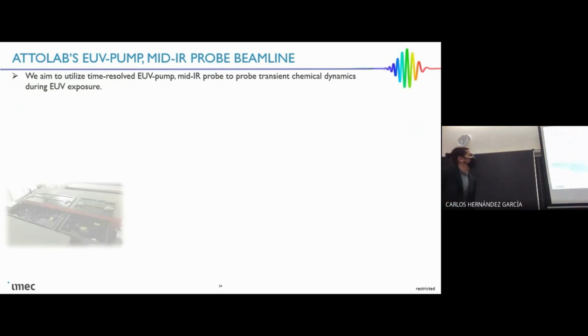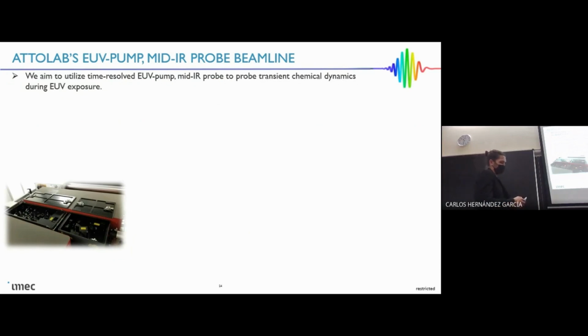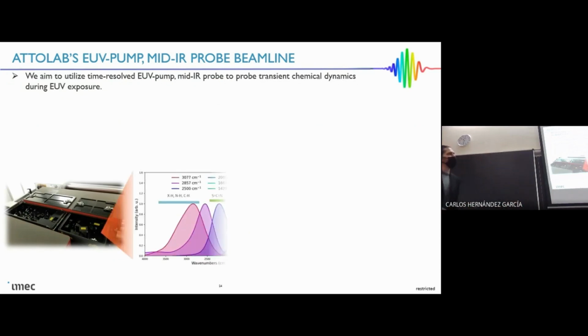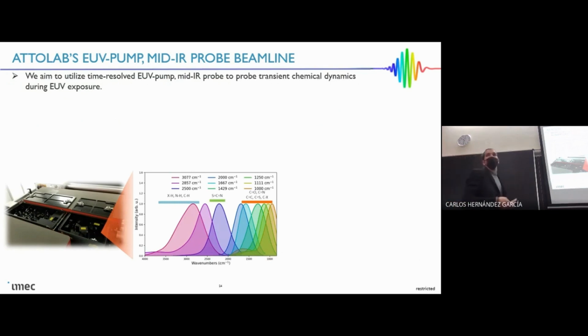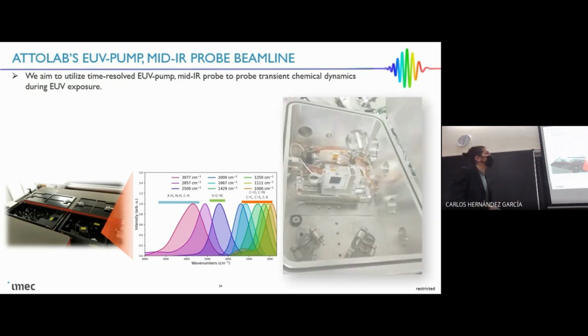And so to generate this mid-IR light, I mentioned we have an OPA. This OPA is quite tunable, quite stable. It produces nice broad spectra. This is in wave numbers, but this is probably 3 microns to about 12 microns, somewhere in there, and allows us to cover a lot of the vibrational modes that are characteristic to photoresist materials.